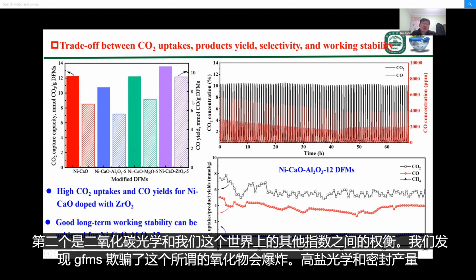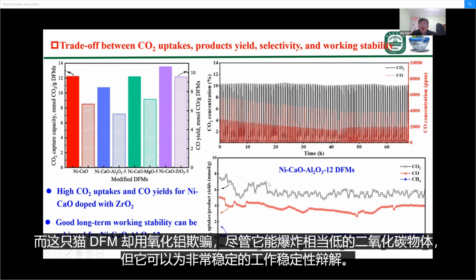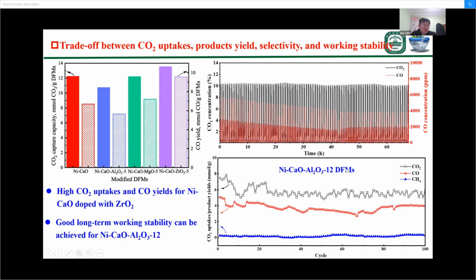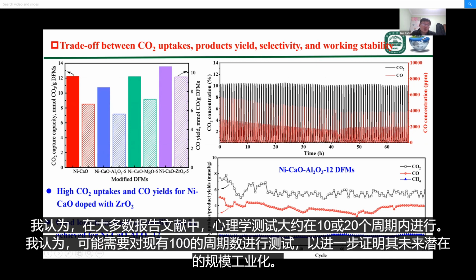The second is the trade-off between CO2 uptake and other indices. In our work, we find that the DFMs doped with zirconium oxides can exhibit high CO2 uptake and CO yields, while the DFMs doped with aluminum oxides, although they exhibit rather low CO2 uptake, exhibit very stable working stability. I think in most of the reported literature, the cyclic test is performed in about 10 or 20 cycles. I think tests with cycle numbers exceeding 100 might be required to further demonstrate its potential in future scale industrialization.